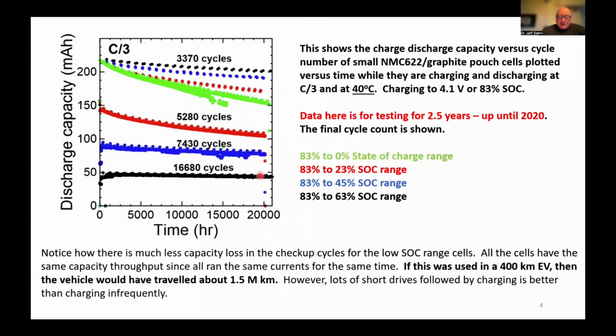So what you see is that when you do a small SOC range, the capacity retention is amazingly good. And what we do is periodically we do a complete what we call a checkup cycle, where we test the cells over the full state of charge range. And you can see that even though you have the same amount of energy throughput in the cell, when you are doing these small depth of discharge cycles, the capacity retention is way better than it is in the case of the green cell. So what this means is a lot of short charges of your EV is better than leaving the cell to go all the way down to, for example, 20% or 10% and then charging it all the way back up again.